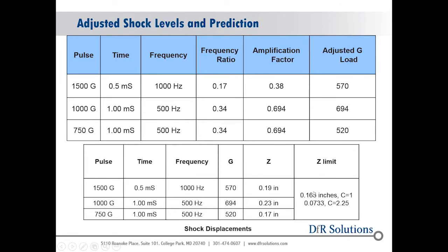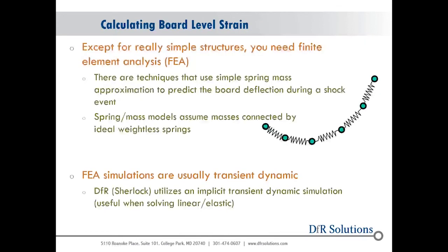And then if I put it into the equations, it pretty much says my Z limits for that part depend on a BGA. Usually you're using a component factor of 2.25, or it's around 2 something. It's been modified a couple times for BGA devices, which means I can have about a 73 mil deflection. If I had a leaded part, usually your component factor is 1, it would be at least 163 mils. But you can see here the actual Z deformation during that shock pulse, calculated using the Steinberg equation, is much higher than both of these. So this would be a no-go type of prediction.